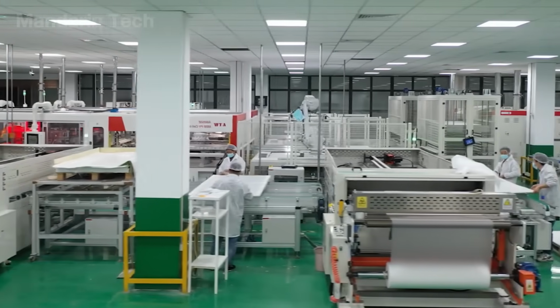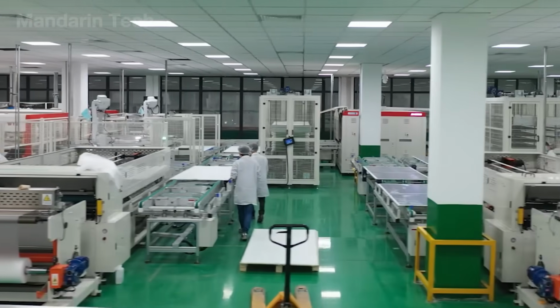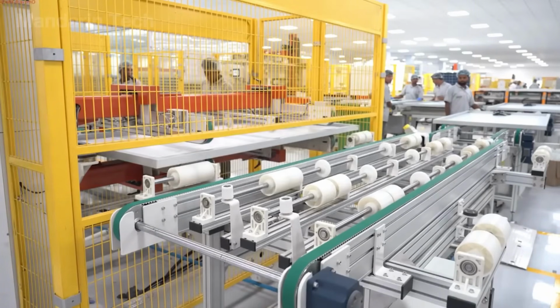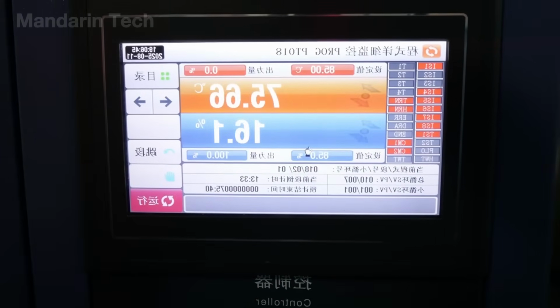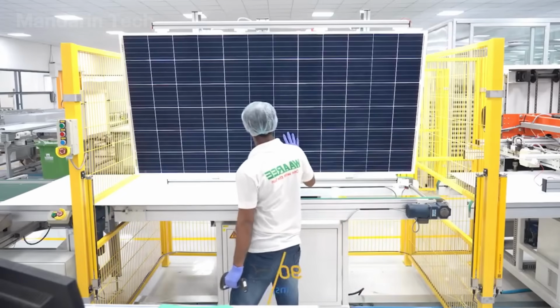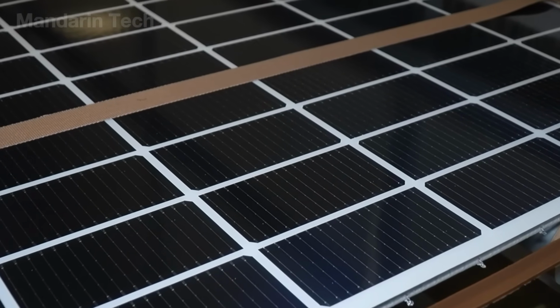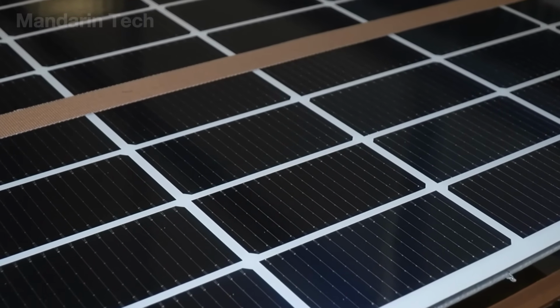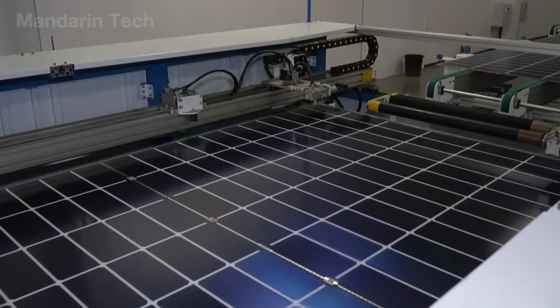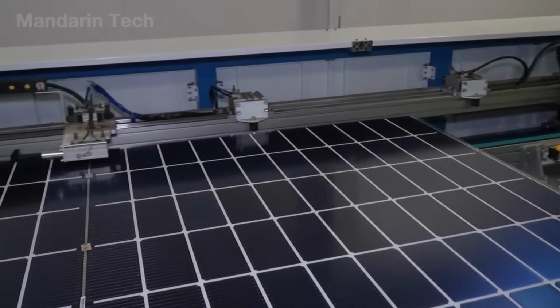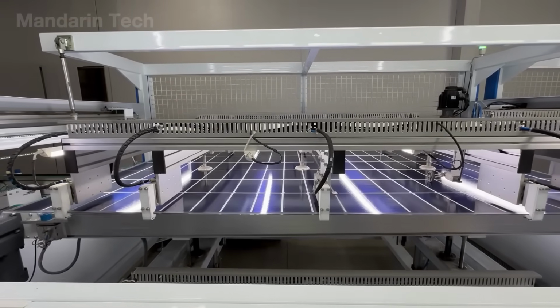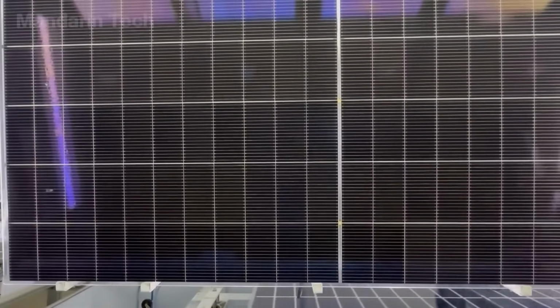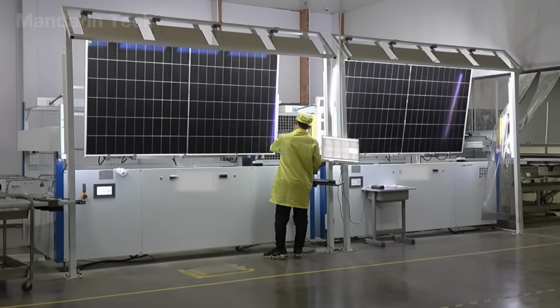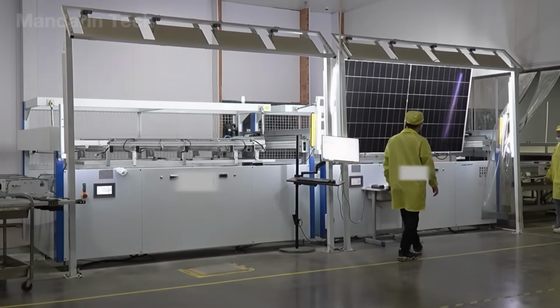From the light inspection room, the panels enter their real trial by fire, proving they can survive harsh natural conditions. Each module is exposed to 1,000 W/m² of light and over 85 degrees Celsius for hours, then sprayed with salt mist to test corrosion resistance, shaken to simulate sandstorms, and frozen at minus 40 degrees Celsius. Current, voltage, and efficiency are measured hundreds of times to detect any deviation. Only panels meeting IEC 61215 and IEC 61730 standards earn certification for global use.